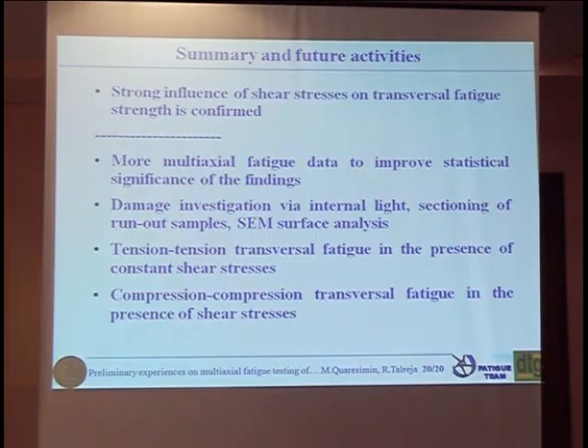Starting from the results we got, we are more interested in the damage evolution. However, in this case it is really difficult to investigate the damage evolution because we basically have a sudden failure due to the specific configuration — the growth of a single crack, usually in mode two or mode three, and then propagation all along the sample. It is therefore difficult to identify stiffness changes or stable crack propagation. We used infrared thermography with a lock-in procedure and internal light investigation, but we are not able to find any indication of stable growth.